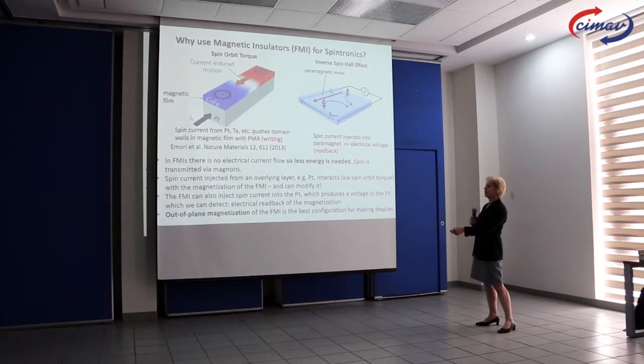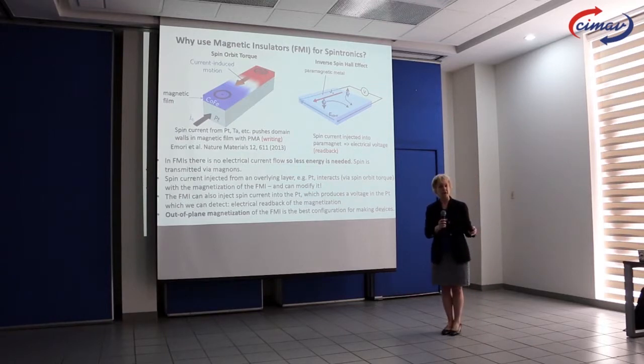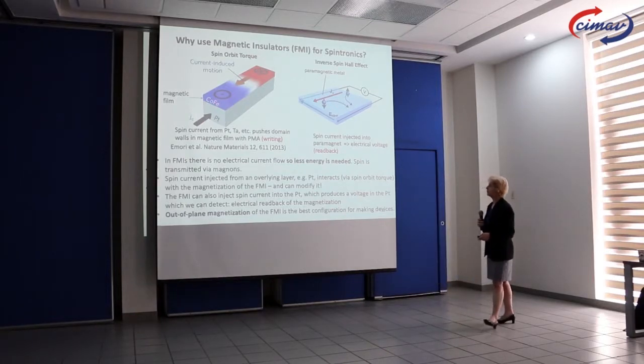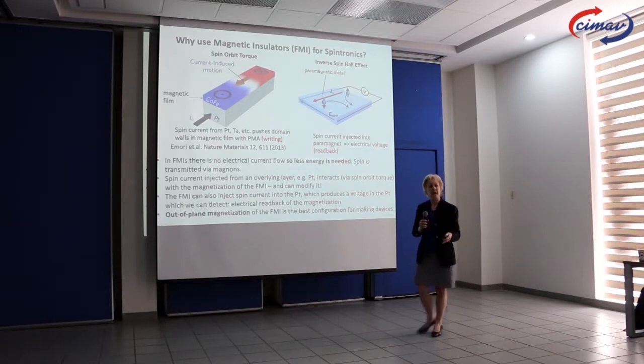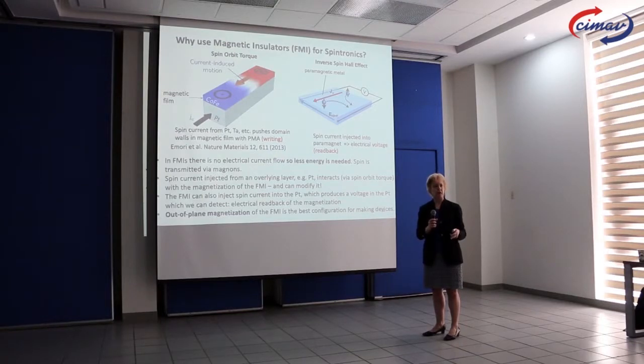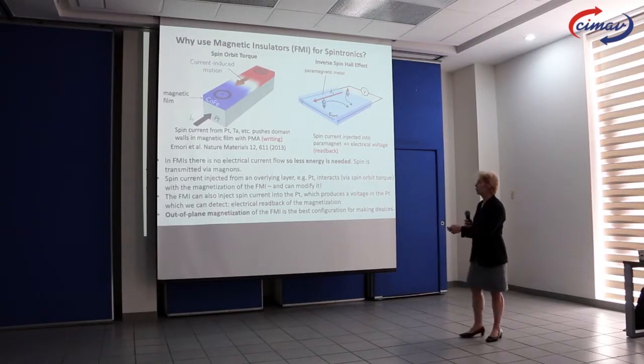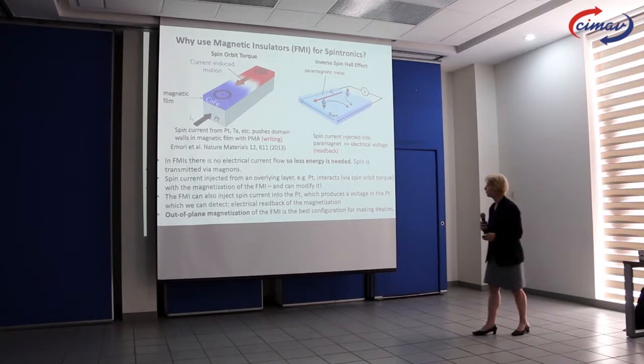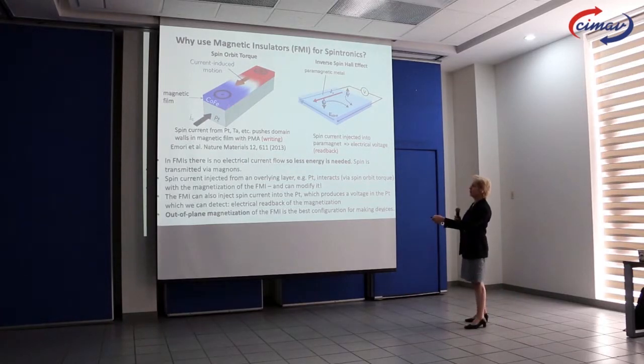So the big argument in favor of ferromagnetic insulators, FMIs, is that there's less energy required to switch the magnetization than there would be if you had a magnetic conductor. Okay, so that's the first advantage of it. It also means that we can clearly separate out different effects. For example, if current passes through both layers and the magnetization of this layer gets affected, we don't really know what's going on. We don't know if it's due to the current in the cobalt or the current in the platinum. But for the magnetic insulator, we know that the current in the platinum is the only place where current is flowing. Okay, so what we're going to do then is make some structures where we have a magnetic insulator, a garnet, and we have platinum on top of it, and we flow current through the platinum.